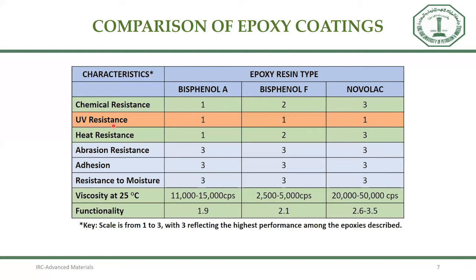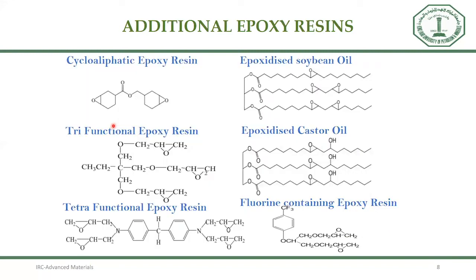So whenever we use these epoxy coatings in atmospheric conditions, we can use some hybrid epoxies. That means we can add some kind of UV resistant polymer like polyurethane, or we can add some metal oxide nanoparticles, which can improve the UV resistance of the resultant epoxy matrix. So these are some examples of additional epoxy resins: cycloaliphatic epoxy resin, trifunctional and tetrafunctional epoxy resins, and some bio-based epoxy resins from soybean oil and castor oil. And there are some halogen-containing epoxy resins with fluorine or bromine, like that.